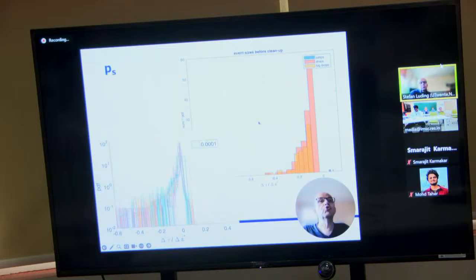Now, when you do the analysis, you get a lot of data, a lot of statistics, and then you want to clean up and plot a histogram which involves the jumps, the drops, and the big drops. And we want to understand whether the small drops are really relevant, whether the big drops are more relevant. The big drops are the interesting ones, by the way. A lot is going on. Okay, and then we can do statistics, and we get something like average change in stress, average change in modulus, and some other things, as you will see on the next slide.